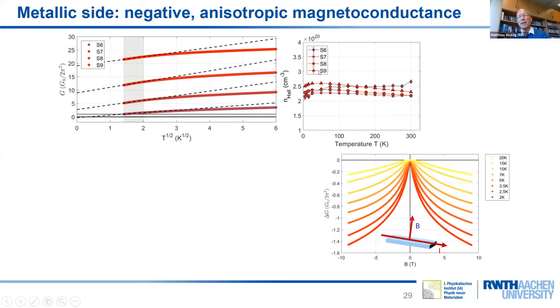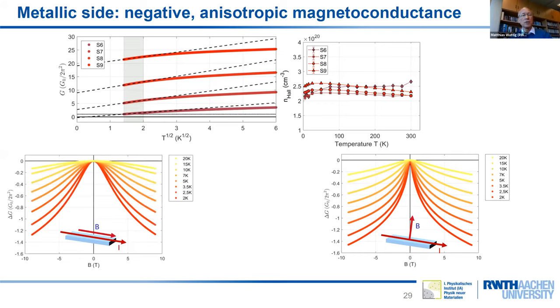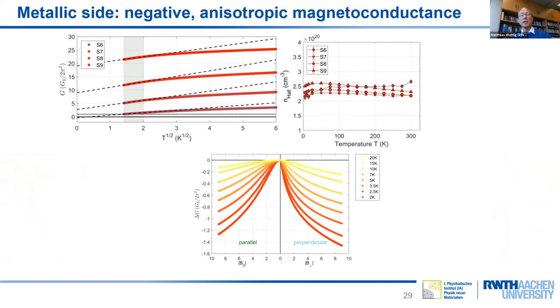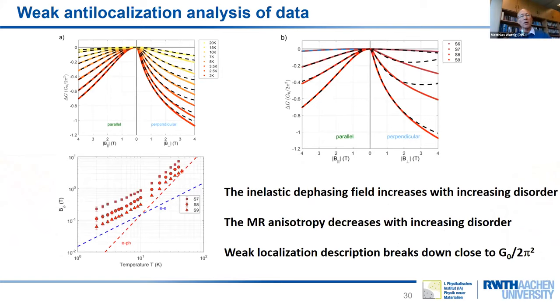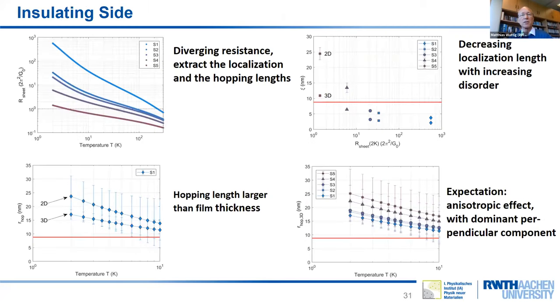We can look here at the magnetoconductance, so in the magnetic field, and you see that for the perpendicular direction, we have this sharp cusp. For the in-plane direction, this is how the curves look. And if you compare the two, then we see that this here is a clear case of anisotropic magnetoconductance. And this is the hallmark of weak antilocalization. We have fitted the data, and you can see from these dashed lines that this is a high quality fit. The important message is that the inelastic dephasing field increases with increasing disorder, and the MR anisotropy decreases. The anisotropy gets weaker and weaker with increasing disorder. And this weak antilocalization breaks down once we are moving too close to this critical conductivity.